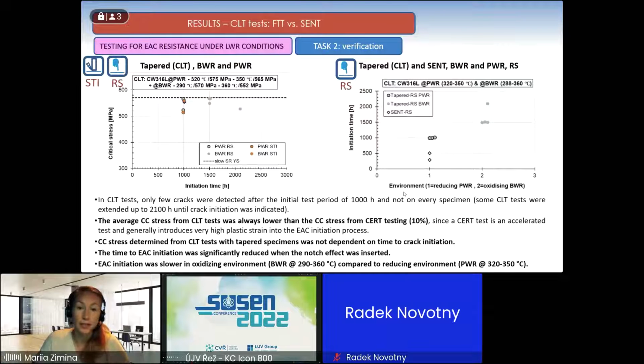For the constant load tests using flat tapered tensile specimen and notched specimen, we detected only a few cracks after the initial test period of 1,000 hours, and as I mentioned already, not on every specimen. So some tests were performed for longer time, up to 2,100 hours, and the average critical stress from this constant load test was always lower than the critical stress from CERT testing. And the reason why is it so? It is because the CERT testing is an accelerated testing, and it introduces high plastic strain into the EAC initiation process. That's why those values differ.